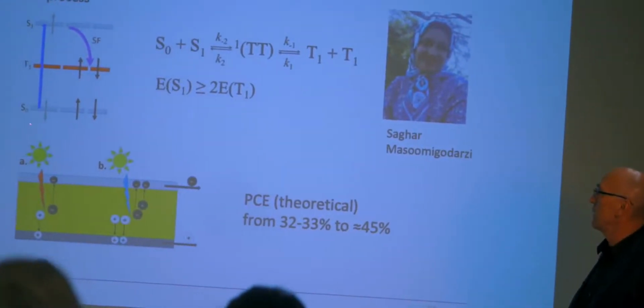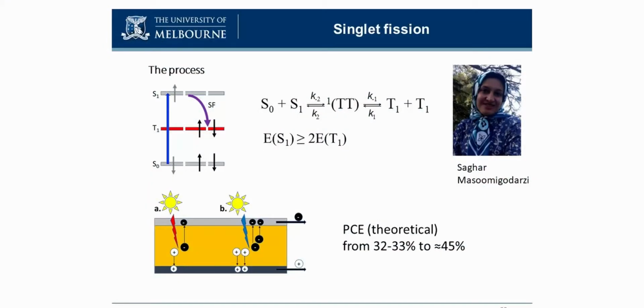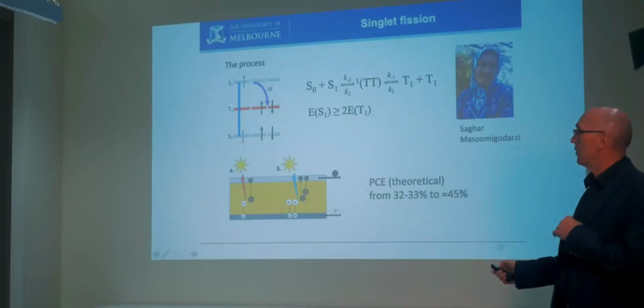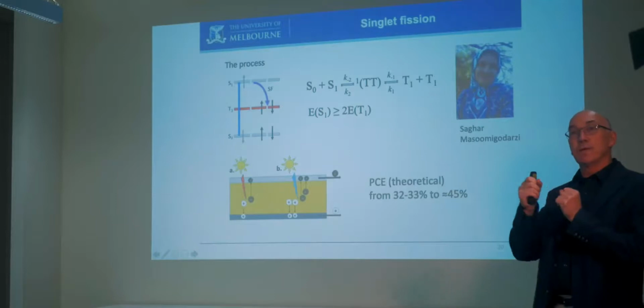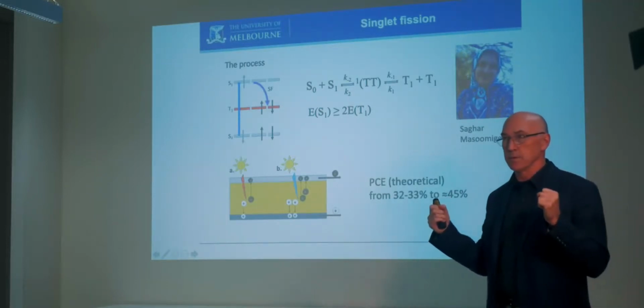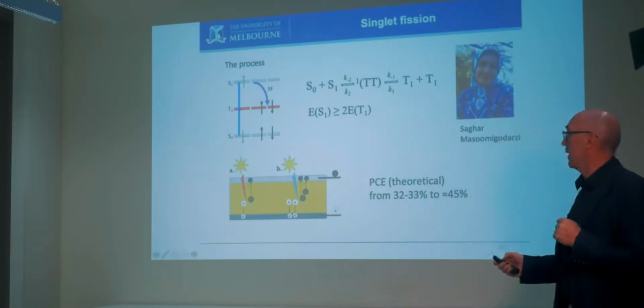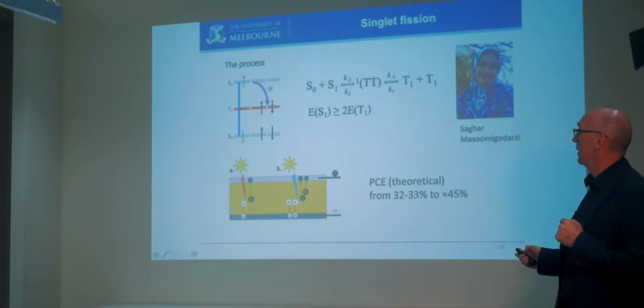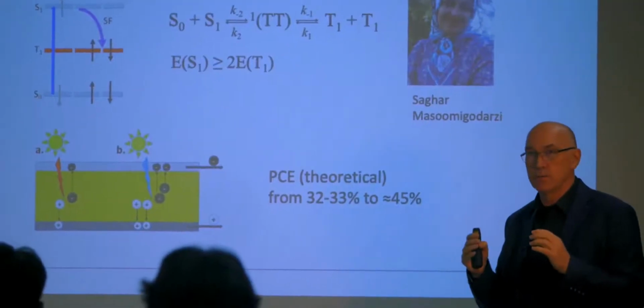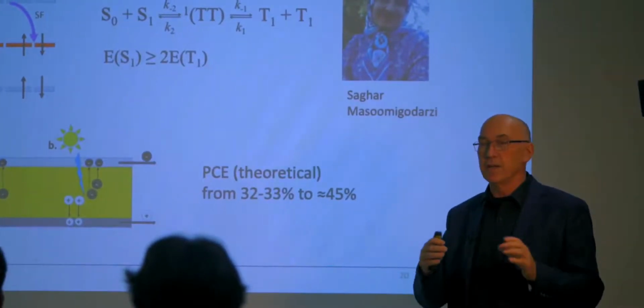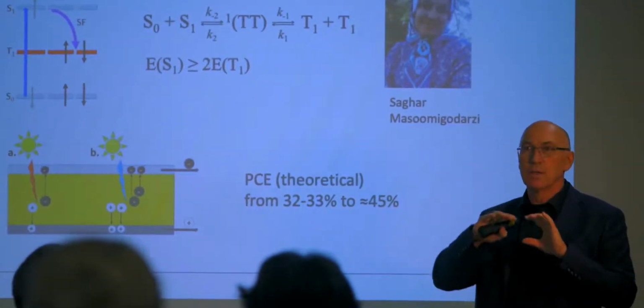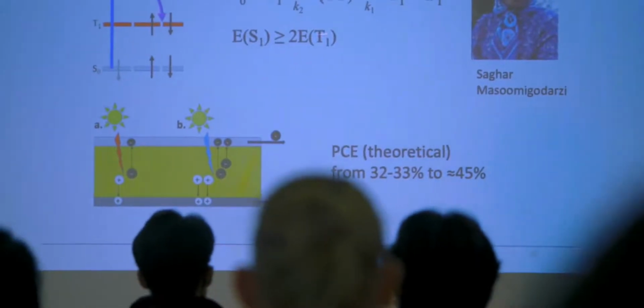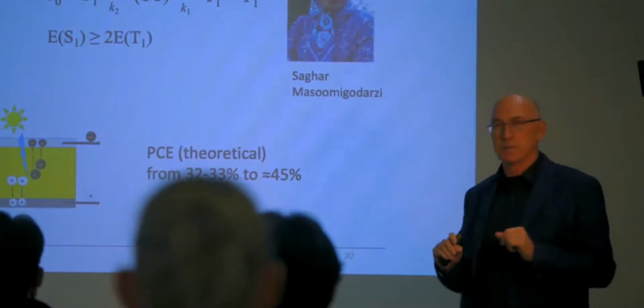Okay, so this is where we need 2 chromophores. So we have 2 molecules that we're going to use. In the first molecule, we excite up to the singlet state, and we use that energy to get a triplet state, which is half the energy of the singlet, and then we need another molecule, and we share that energy between 2 molecules. So what we're doing now is taking 2 molecules, one in a ground state, one in a singlet state. We're sharing this energy between these 2 to make initially a correlated triplet pair. Okay, so this is a very advanced process of basically forming this quantum coupled state. And so we get a correlated triplet pair, but this is allowed from spin theory.